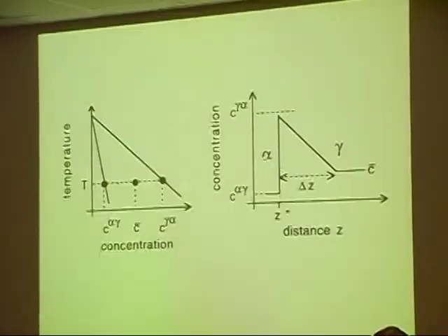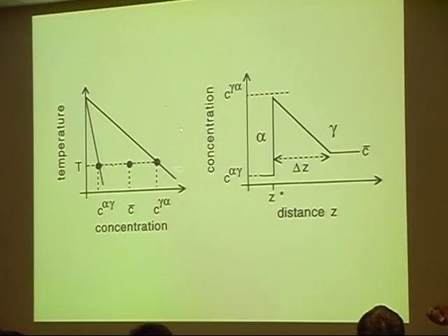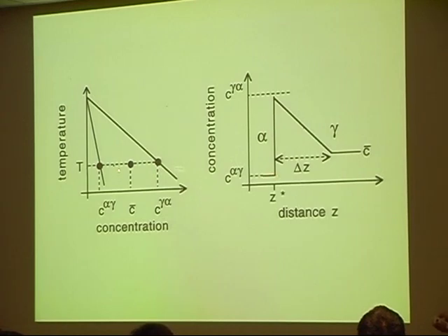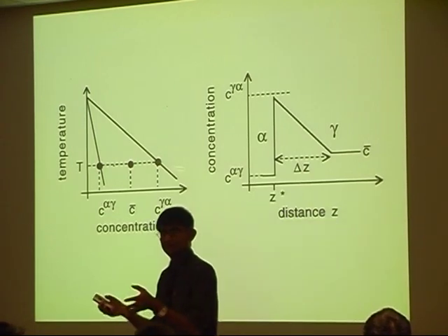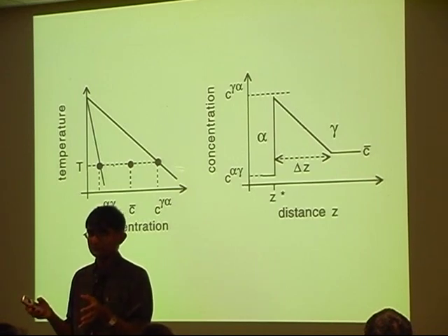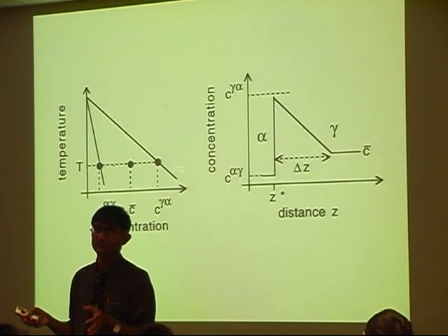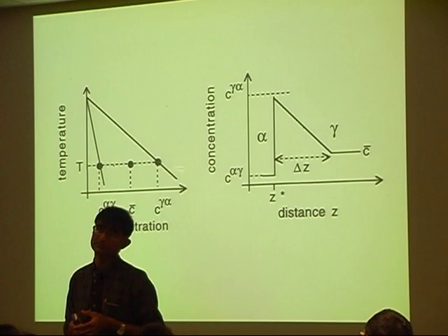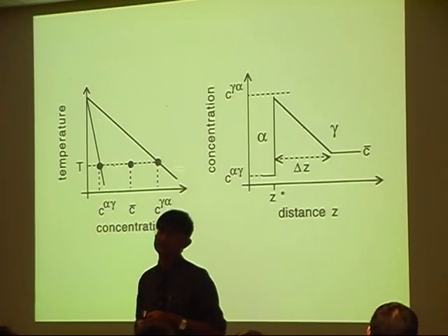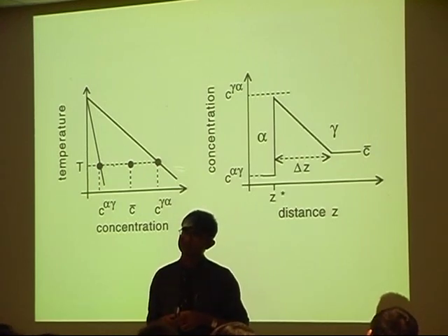let's imagine that this is ferrite, which is growing in austenite, and I'm plotting the carbon concentration here. Then this point here comes from the phase diagram, and this point here comes from the phase diagram as well. So with kinetics, you can't do without having the thermodynamics. And you combine the two and you also get the time dependence. Without thermodynamics, we could not do any kinetic calculations. And the other thing is, it also sets the rules. If the free energy change is not negative, then it's impossible for the reaction to happen. So you can say what direction the reaction can happen or not happen. Does that roughly answer?